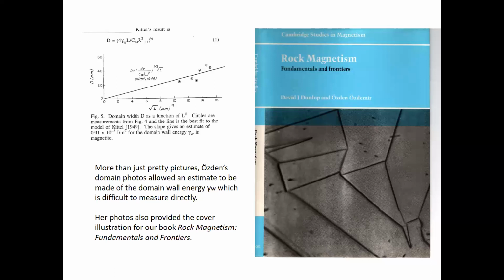Now, they're more than just pretty pictures, because by looking at the width of the lamellar domains versus their length in this graph on the upper left, you can get the domain wall energy, which is not something you can readily measure, but it's something that theoreticians need in order to do modeling. And the value comes out spot on 10 to the minus 3 joules per meter squared. Used to be even easier. It was 1 erg per centimeter squared. That was really easy to remember. And of course, her photos also provided a nice cover for Cambridge University Press for our book.